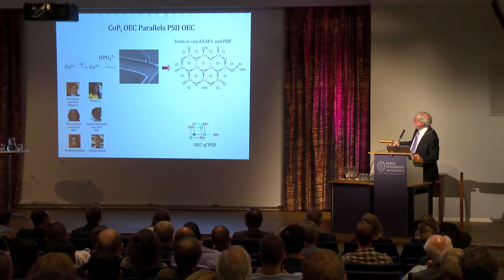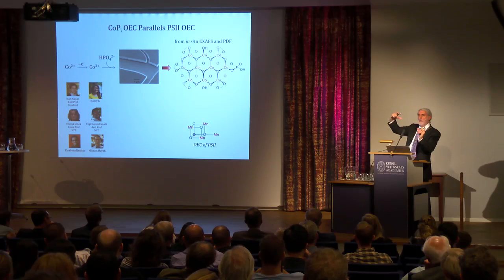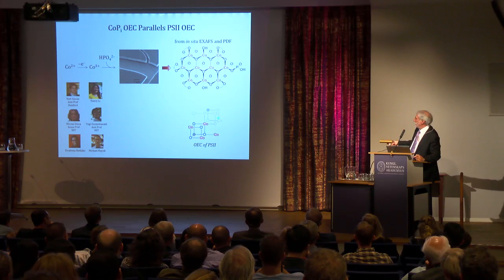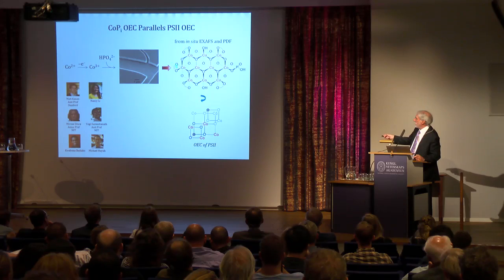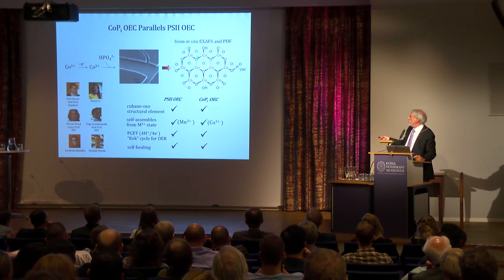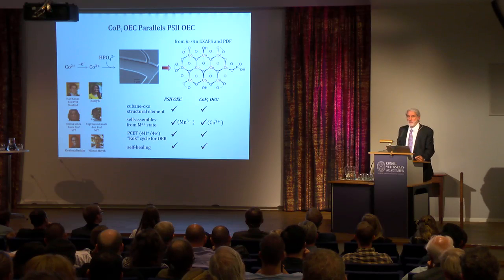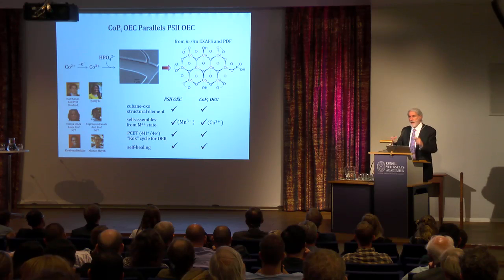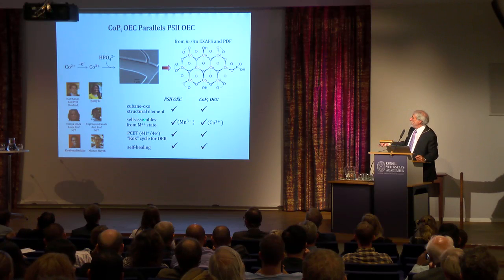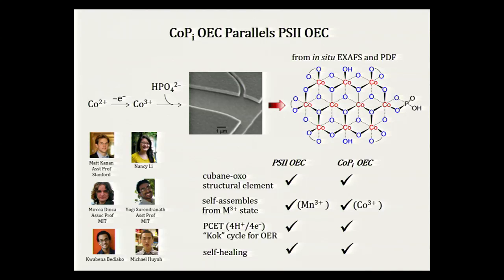So if you take that cubane, and now I take it and do a head-to-tail dimerization. Now I'm going to put cobalt in place of manganese. I rotate it by 45 degrees. I get that. So it turns out, structurally, this looks like the oxygen evolving complex. It's catenated cubanes. It self-assembles. You don't have to do any synthesis. You just have to put current in solution, oxidize cobalt-2 to 3. You don't need to know any chemistry. It will spontaneously make this once you get this to cobalt-3 in the presence of phosphate.